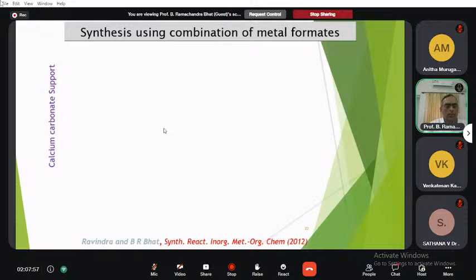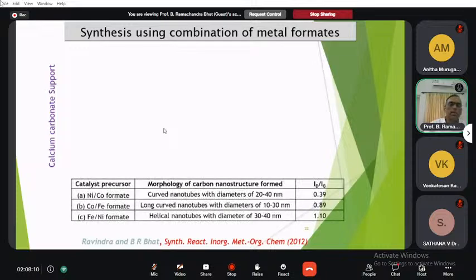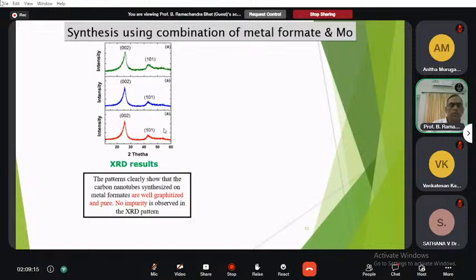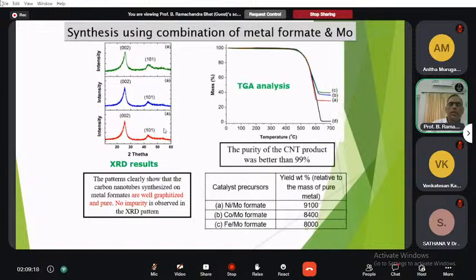So we have discovered a few metal formates for the synthesis of the carbon nanotube on calcium carbonate as a support. These metal formates are like nickel and cobalt formate, cobalt and iron formate, and nickel and iron formate. No impurity is observed in the XRD pattern. You can see the TGA analysis of the CNT thus prepared. The purity is better than 99%, and the yield is also very high.